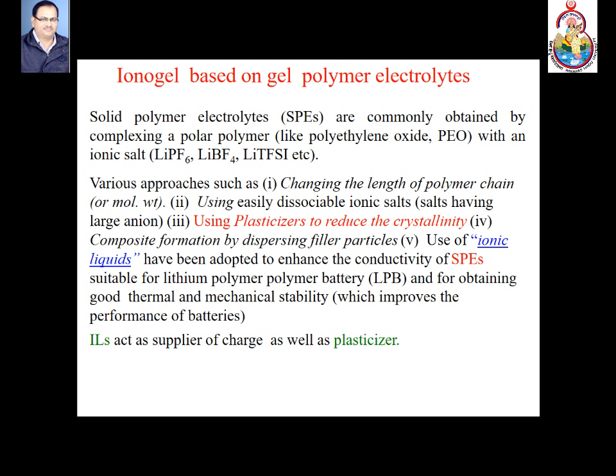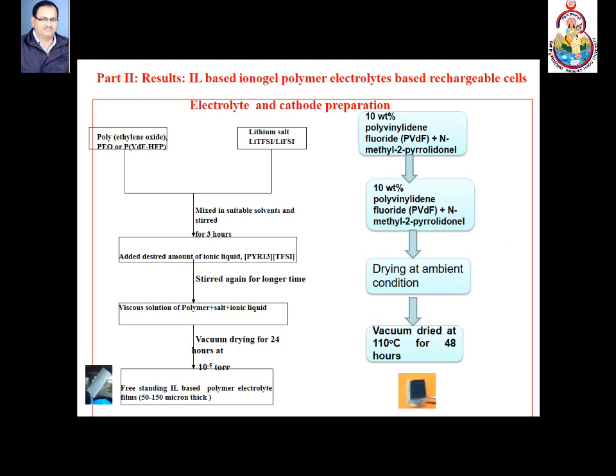It may be recalled here that a number of companies have recalled lithium batteries which were at risk of explosion due to safety issues. Even the Dreamliner 787 was grounded, which was due to a problem in the lithium battery used in it. Ionogel polymer electrolytes can be synthesized by the conventional solution cast technique, and polymeric membranes can be obtained in desired shape. The cathode can be synthesized by dissolving the active cathode material in binder PVDF-HFP, solvent NMP, and electron conducting agents like carbon, and then these can be coated on aluminum current collector in desired shape.